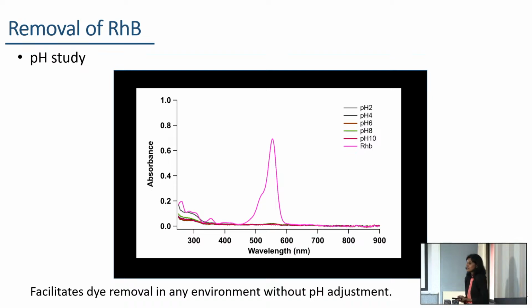That confirms that the rhodamine B dye is adsorbed onto these GEO-based materials via the partially reduced graphene oxide through pi bond interactions. Because if electrostatic interactions were involved in the rhodamine B adsorption, then the dye removal would be greatly affected by variations in pH. So from this independent nature of dye removal with the variation of pH, we can further confirm that rhodamine B is adsorbed onto this composite through pi bond interactions.